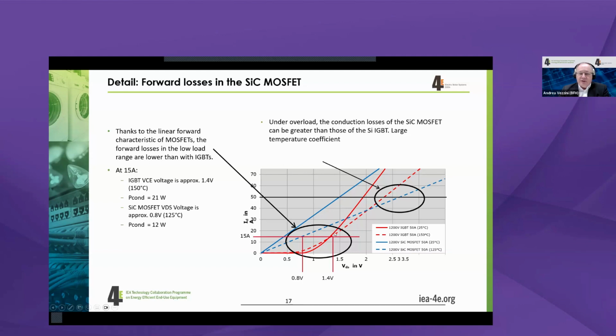But as you can see, the voltage drop here for the silicon semiconductor is getting closer to the silicon carbide element, and it's probably crossing here somewhere at currents of 85. What is more important is that silicon carbide has a positive temperature coefficient, so with higher temperature, and this dashed line is at 150 degrees, you can see that there is a turning point, which is here at about 40 amps, where the IGBT actually has a higher current capability than the silicon carbide.